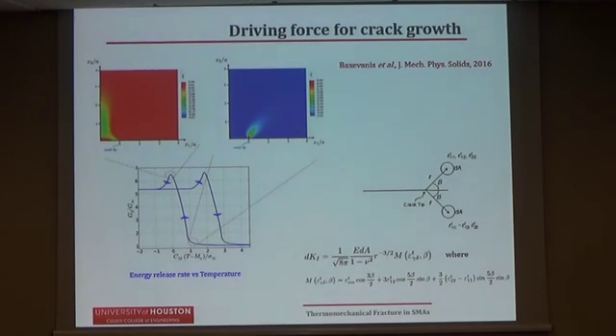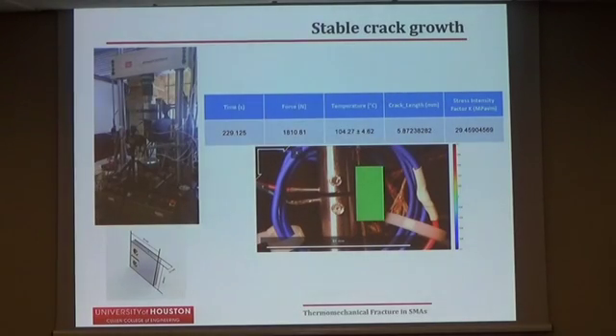With the same arguments, we can explain what happens during phase transformation during heating. So it is possible during cooling that as the driving force for crack growth increases, we may reach the material-specific critical value and the crack may start growing. Okay, so next, what we wanted to see, the previous experiments were in a very unstable crack configuration.